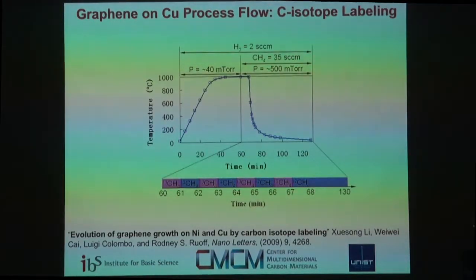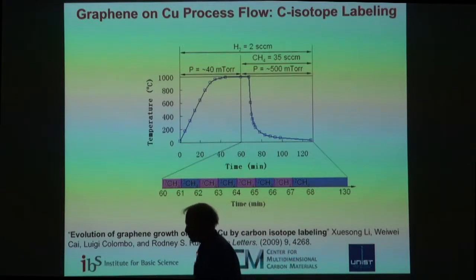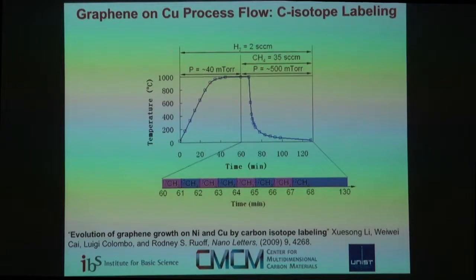So one thing that was very interesting about our results on copper was that we shouldn't have gotten those results in terms of the thermodynamics. That is to say, the binary phase diagrams that have been published. So we found two papers in the literature, and we chose copper because we thought the solubility of carbon in it was at least very small, but not zero. So those two papers differed in their concentrations of carbon at equilibrium in copper at 1,000 degrees Celsius. But it's very small in either case. In one case, it's a few ppm. In the other case, it's hundreds of ppm.